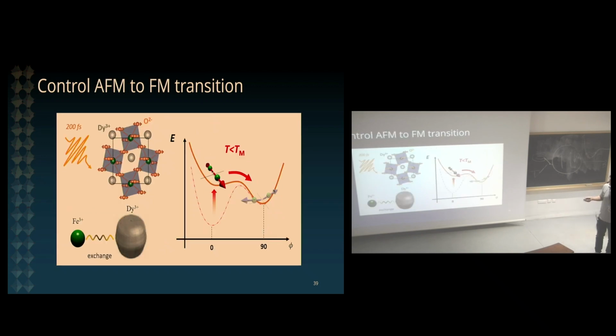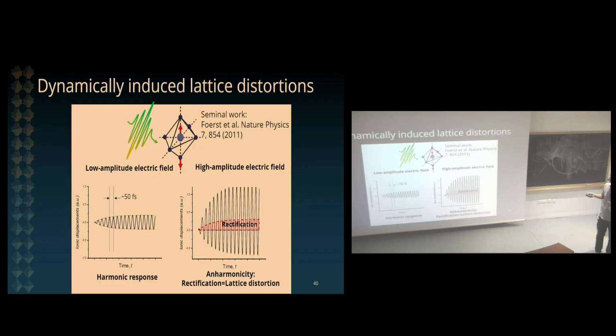Right. So our idea was the following. Can we excite the lattice, bring our oxygen octahedra out of equilibrium, create a crystal structure that has a certain lifetime, and this will entail a modification of the antisymmetric superexchange between iron and dysprosium, which in turn will modify the energy landscape and possibly induce a transition between these different states? Okay, so that's the idea of the experiment.